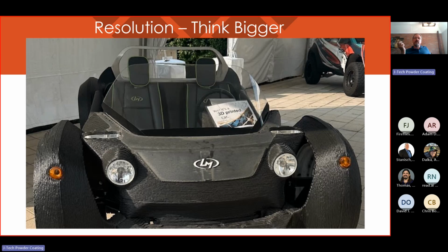All printing has similar considerations for layer time and cooling. If your layer times are too short, the previous layer may droop. And if your layer times are too long, it may be cooled down to the point where adhesion is poor, resulting in delamination.